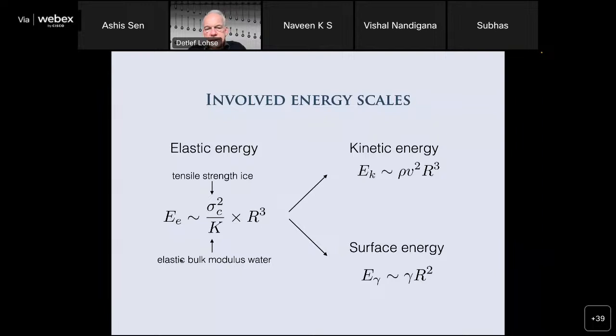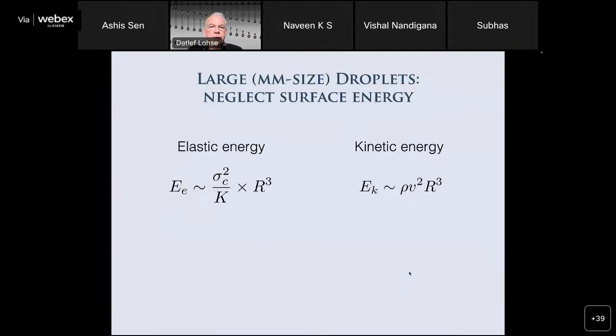Here I put in some elastic bulk modulus of the water and the tensile strength of the ice, which is about known. This, of course, depends on how exactly you make the ice, so there is some variation in this. And this elastic energy goes into kinetic energy for the breakage and for the surface energy. Kinetic energy, of course, goes like R cubed, but also like velocity squared, with this typical velocity of these parts flying apart. And surface energy goes like R squared.